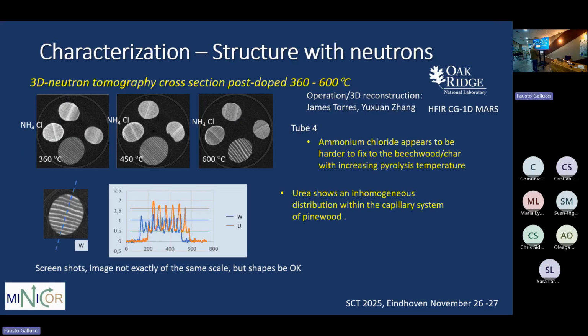The next step is we pyrolyze it. So here we see the pyrolyzed samples, and we see that they get deformed, so they shrink more along the ring than in the radial direction. This is with ammonium chloride, and what you see is some crystallization of ammonium chloride inside when it's post-doped. And it seems to penetrate less the more pyrolyzed it is. And you see quite some rim here. So what gives the signal here is basically the hydrogen in the ammonium. Okay. So you trace the nitrogen through the hydrogen.